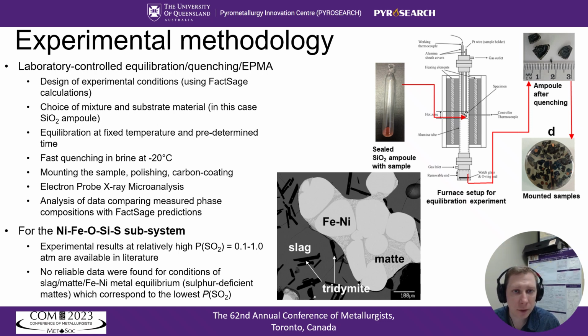The typical experimental steps include designing experimental conditions using FactSage calculation, and the choice of mixture and holding material. In this case, we use the silica substrate. After several equilibration trials and after studying the samples, we select an appropriate equilibration time for a given range of temperatures and expected phases to form. After equilibration, the samples are quenched in brine to preserve the composition at high temperature. They are mounted in epoxy resin, polished and coated with a layer of carbon for electron microscopy.